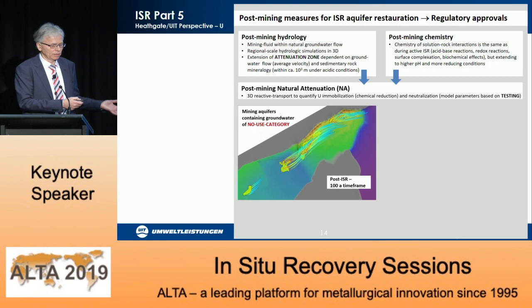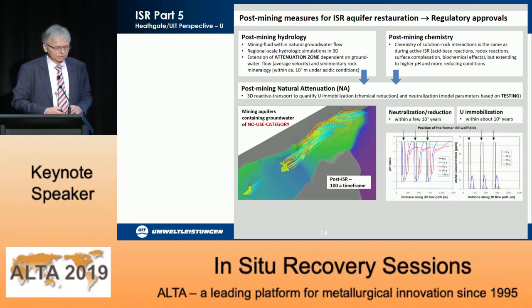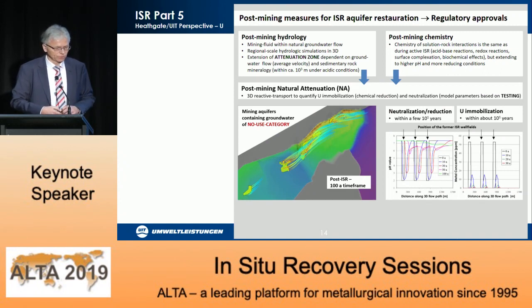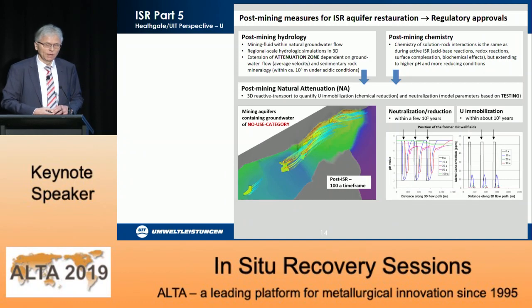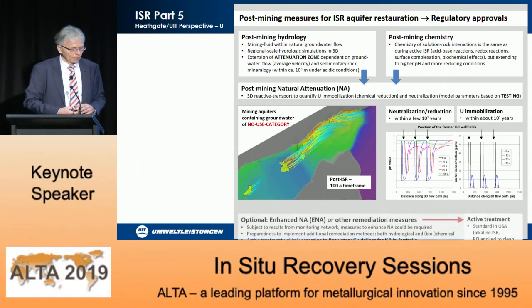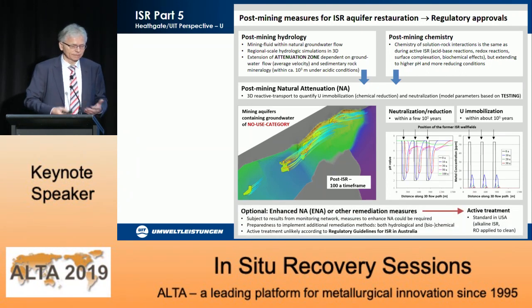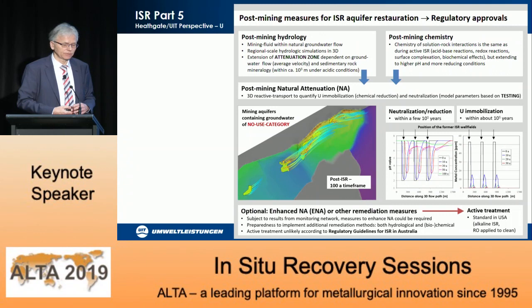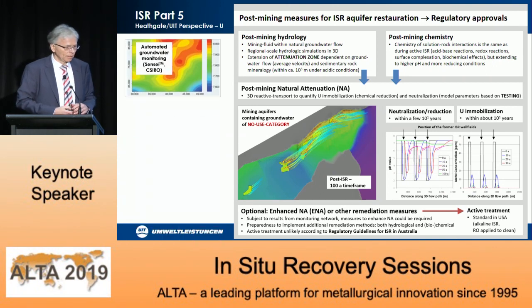There are some figures showing this on a 100-year scale, and by the reactive transport modeling, we simulate this natural attenuation with regard to neutralizing and reducing effects, immobilizing the uranium and neutralizing the lixiviant in the longer term. We have to be prepared to enhance natural attenuation if necessary. Active treatment is not considered in our Australian operation, but it's usual practice in the United States.